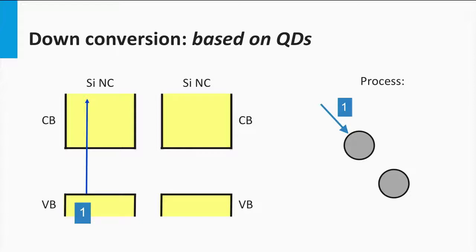It appears that in such nanoparticle systems, the quantized rest energy is not necessarily lost as heat to the lattice, but can be transferred as a quantized energy package to a neighboring quantum dot. Here, a second electron is excited into the conduction band of the second quantum dot. Now we have generated two electron-hole pairs out of one photon.